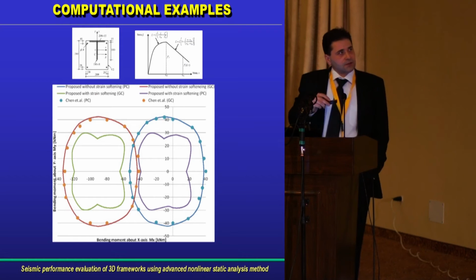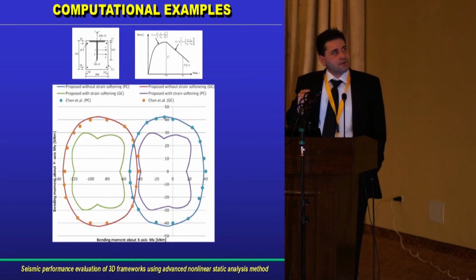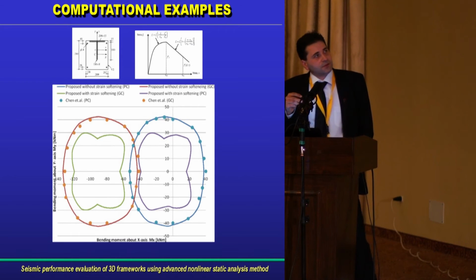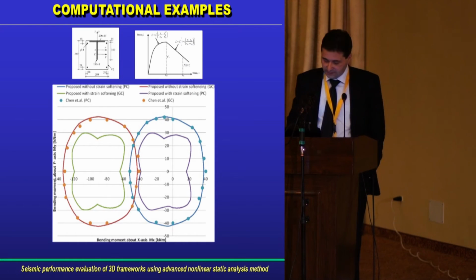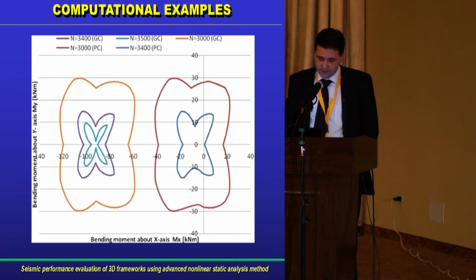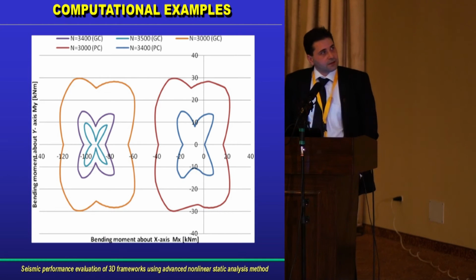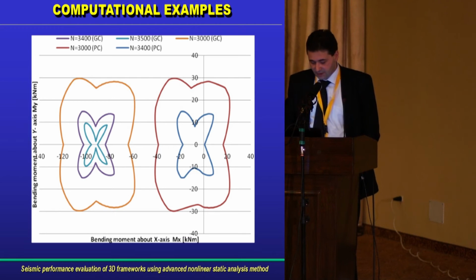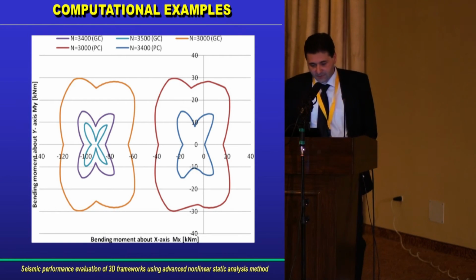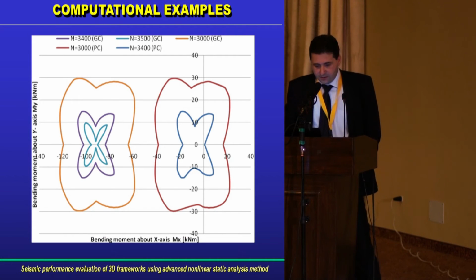And also, most of the numerical procedures developed, found in the literature, have very much difficulties to consider this effect. So the main conclusions of these computer examples is that if we consider the strain softening effect, the capacity curves are non-convex, and also the ultimate strain capacity is reduced. Here, the same issue is highlighted: if we increase the compression axial loads, the ultimate strain capacity is reduced, and also the non-convexity is more aggressive. Such as in these diagrams, here we can see such crazy curves.